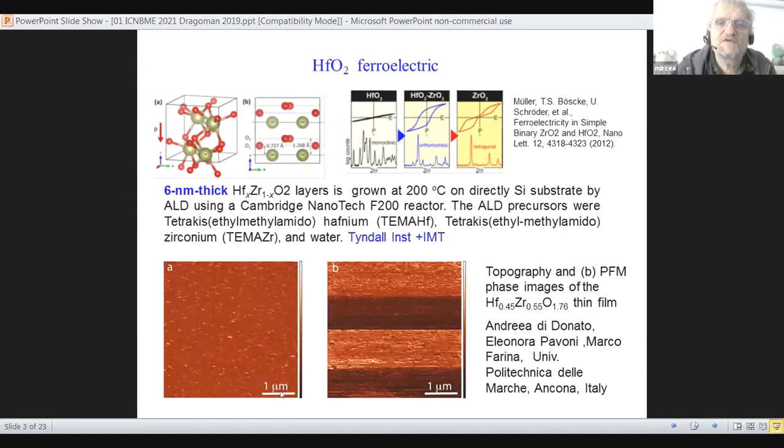A big surprise was that hafnium oxide, which is a typical dielectric used in integrated circuits today, in my laptop, in my telephone, is ferroelectric. It is ferroelectric by doping, creating stress. The stress modifies the atomic structure of the hafnium oxide. It becomes non-centrosymmetric, and for certain doping with dopants like silicon, zirconium, lanthanum, it becomes ferroelectric. This is important because it is the single ferroelectric which is integrated with CMOS technology. I said it was a dielectric in actual CMOS technology.